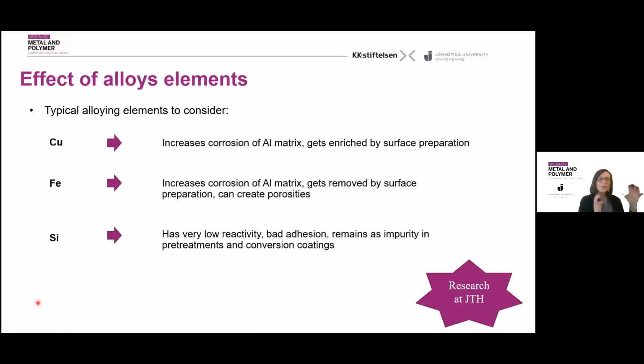Regarding copper, it is really dangerous when we talk about aluminum alloys, because it increases the corrosion rate of the aluminum matrix. When we expose the aluminum alloy containing copper to the preparation steps, usually it gets even enriched at the surface, increasing the alert we should put on this element.